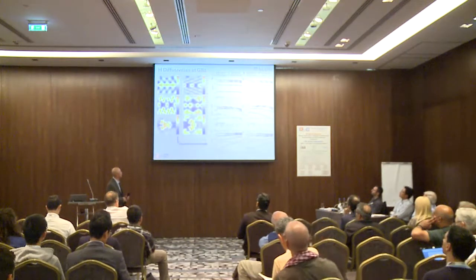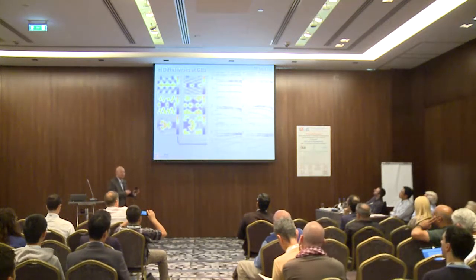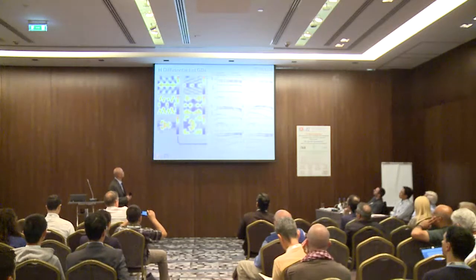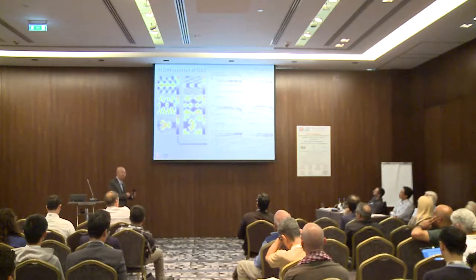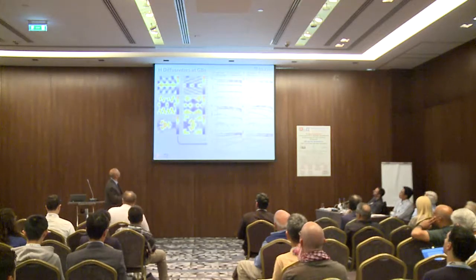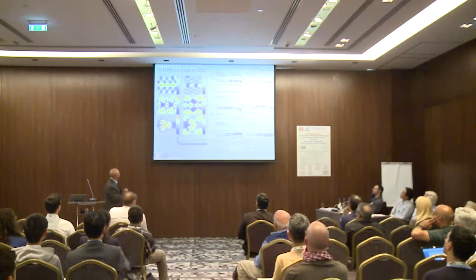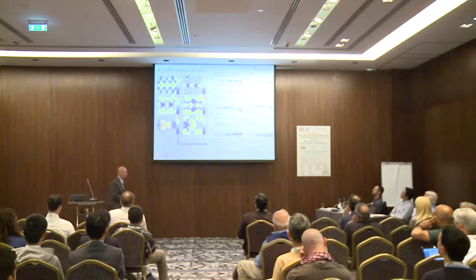If we want to calculate the effective diffusivity, then we need to do kinetic Monte Carlo simulations, which is shown here. I didn't describe the simulation details, but that's basically standard. You take all those DFT calculated barriers as inputs for kinetic Monte Carlo, then you calculate the effective diffusivity for hydrogen along the grain boundary direction. So the diffusivity we're measuring here is for hydrogen diffusion along the grain boundary direction. Apparently for this case, hydrogen diffusion can be anisotropic.